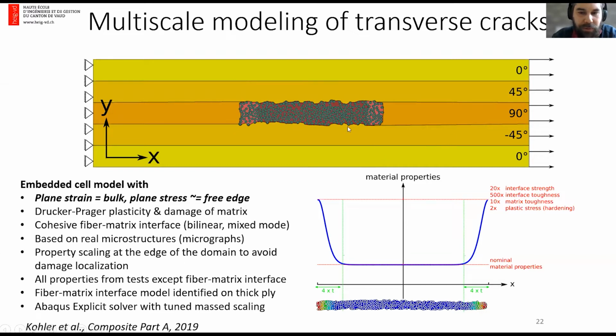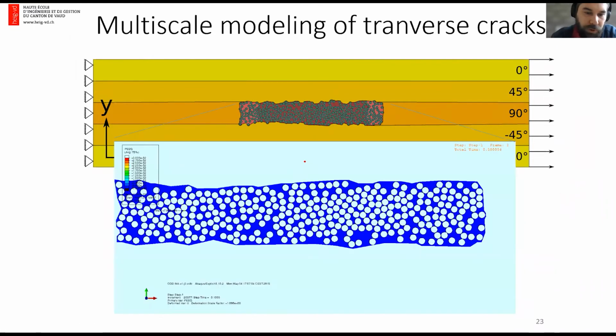And we did this simulation with two types of conditions. One is a plane strain condition in the out of plane direction here, which is the condition that develops in the bulk of the laminate. And the other condition is the plane stress condition, where we have zero normal, out of plane stress, which corresponds to the free edge approximately. And by running this, we can have a look at the damage progression.